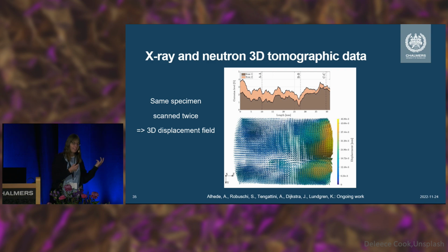And it's not as easy as just putting in the scans and pushing a button and then it's done. He really needed to work a lot with different kinds of filtering and everything. But in the end, what we see here is the displacement field. You can see how this upper side moves in this direction, and this lower side moves in the other direction. So what we typically see is a crack taking place here, or opening up even more.